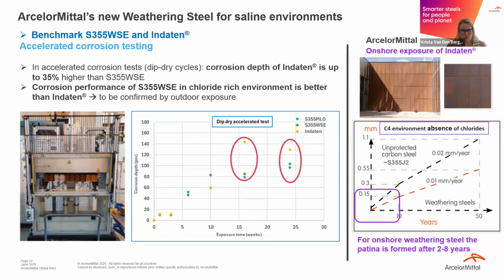So if we now look closer at the saline-resistant weathering steel, its behavior compared to the standard weathering steel, like Mike explained in his presentation, there are application limits for the current weathering steel. So if you have a distance lower than 1 kilometer from the seaside, you cannot use the standard weathering steel, and then maybe the saline-resistant weathering steel can be an option. What we see here is a result we have up to now from an accelerated corrosion test, but our outdoor exposure is running, so we hope to confirm this result in the real outdoor exposure.